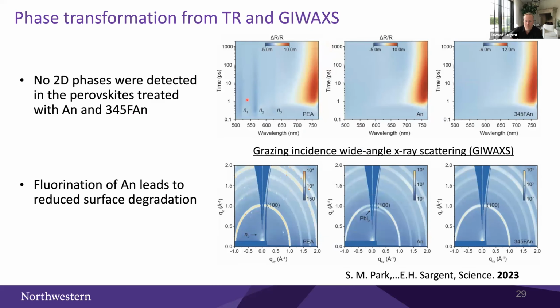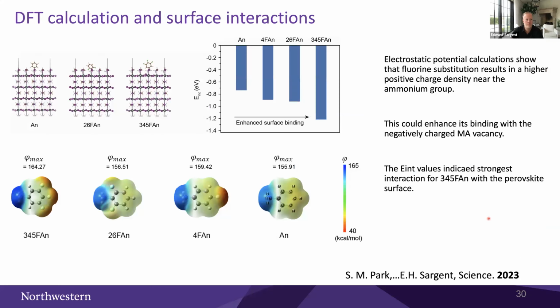And so this is something that, as I mentioned, we can look at with a combination of transient reflectance, and we can complement it with GIWAXS. When we look at the PEA, we see in the transient reflectance the evidence of the 2D phases. We see no evidence of that when we work with either of the two aniliniums. When we work with GIWAXS, we can see evidence of lead iodide forming if we just use the regular anilinium, and we can prevent that through the use of the fluorination.